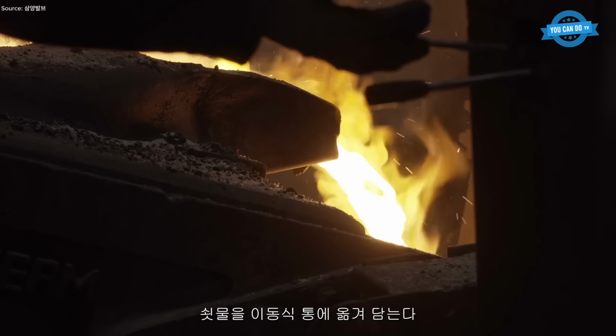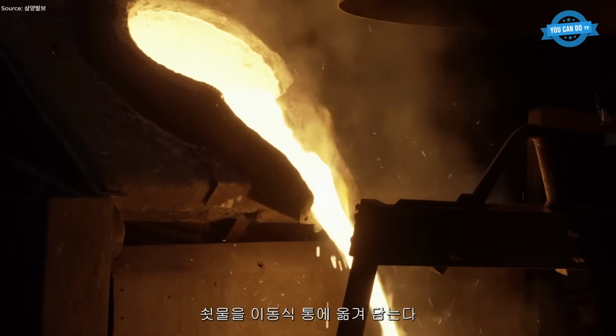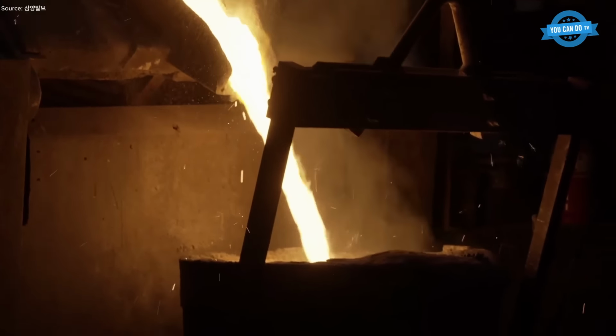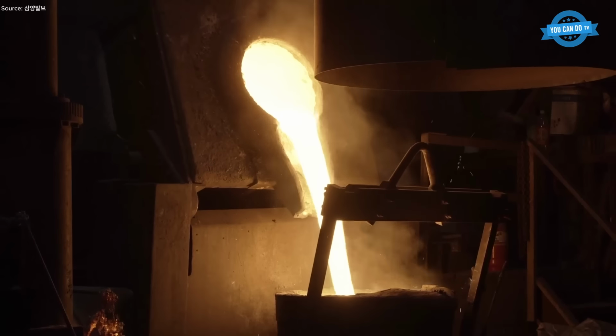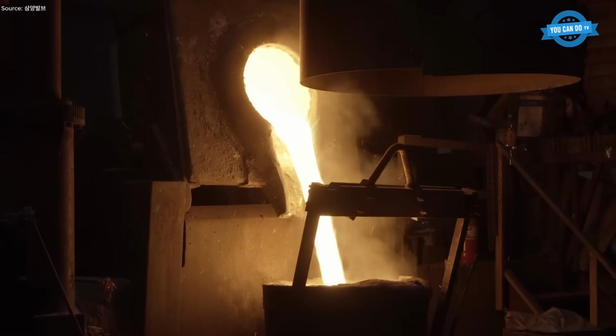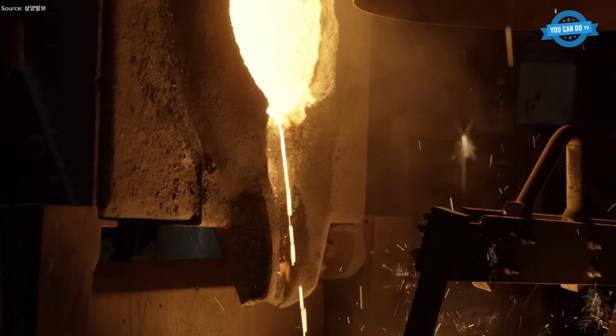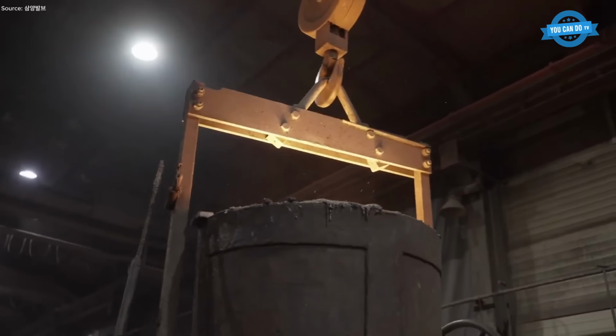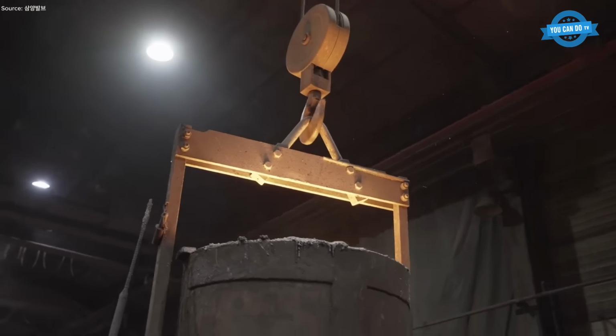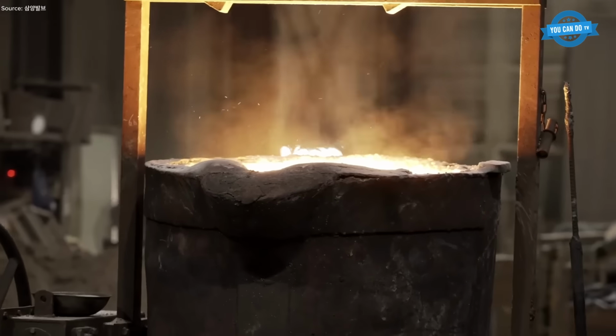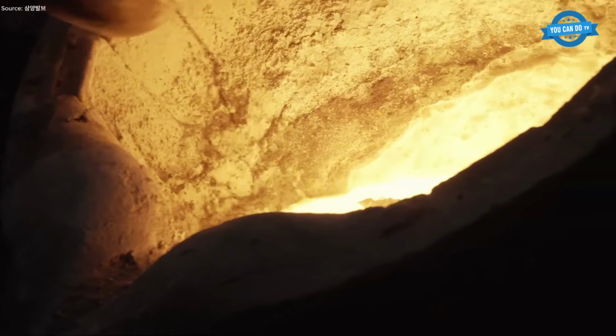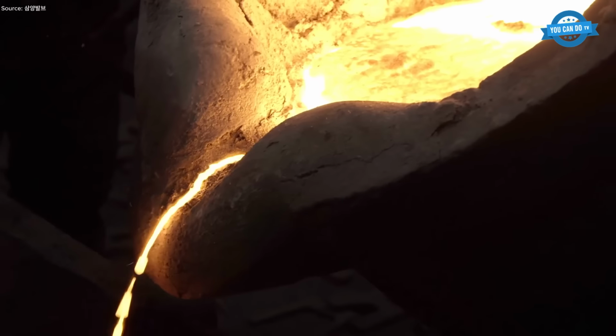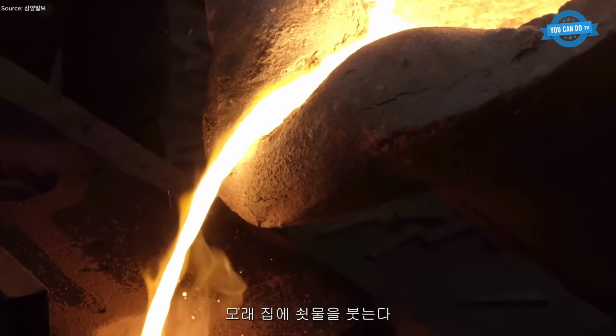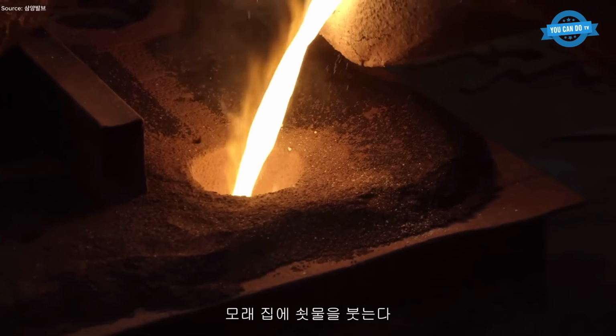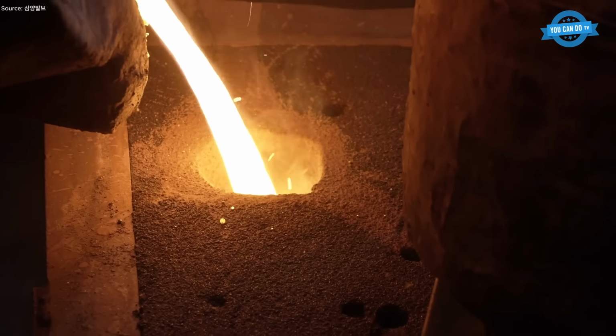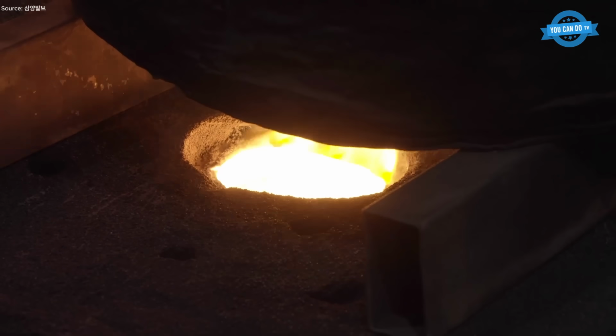Once the metal reaches its target composition and temperature, it is transferred into mobile ladles and poured into the prepared sand molds. The molten steel flows through the gating system, filling the cavity and risers completely. Sufficient metal volume is maintained to ensure that shrinkage during cooling does not compromise structural integrity. Given the mass and thickness of large valve castings, controlled slow cooling is essential. Cooling occurs over several hours, allowing internal stresses to dissipate gradually and ensuring a stable microstructure.